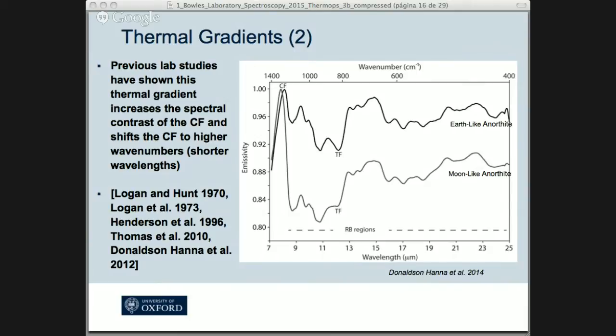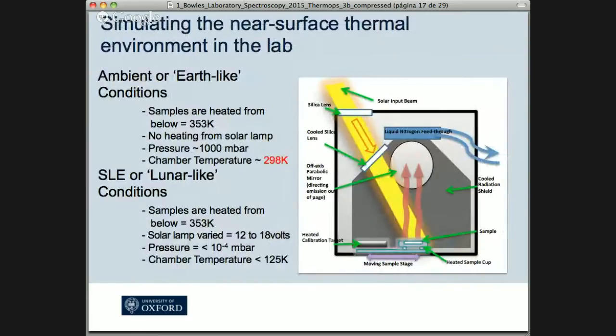So the equipment that we use to do this is we have an environment chamber, and there are a couple of labs all around the world that do this now, and they have a very similar setup. Essentially, you have a cold shield that you cool down with liquid nitrogen. You illuminate the sample from above with a quartz halogen lamp or equivalent to give you some shortwave heating, and then you feed that into your spectrometer. So the spectrometer is kind of attached out to the plane of the picture, and that gives you the kind of lunar environment conditions that we like to see, and we can modulate that and change that for different airless bodies in the solar system. So you can set up the right thermal conditions and see what that does to the spectrum.